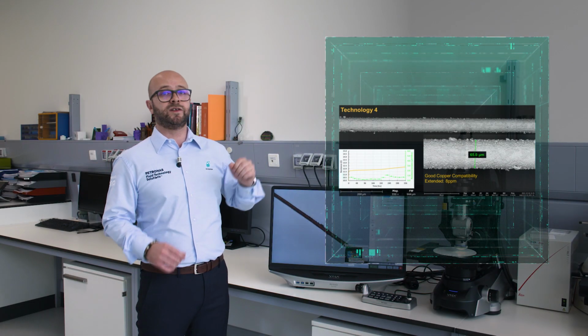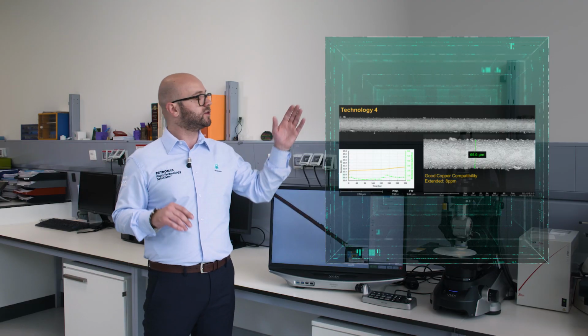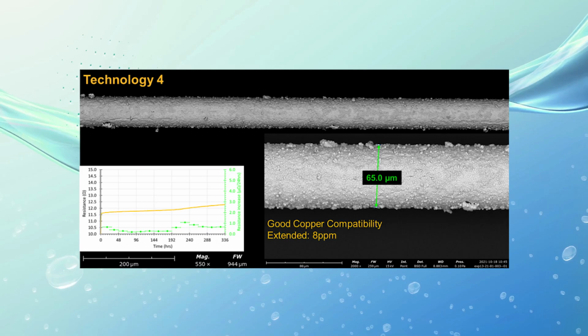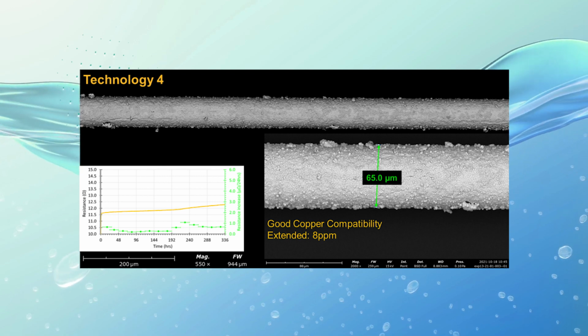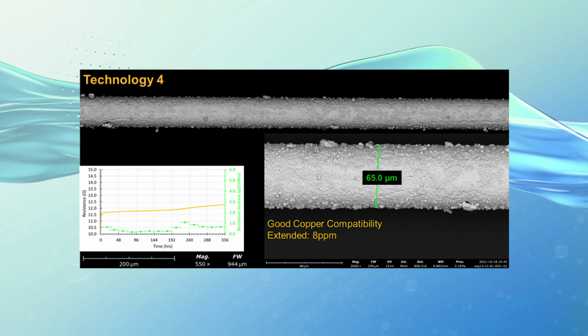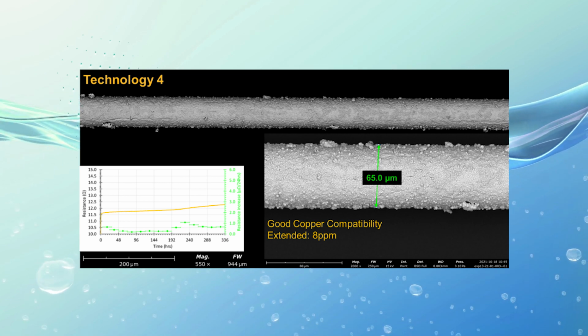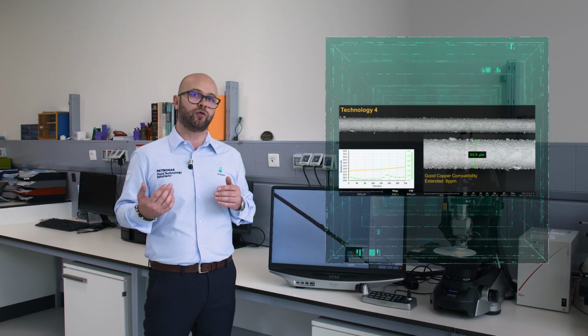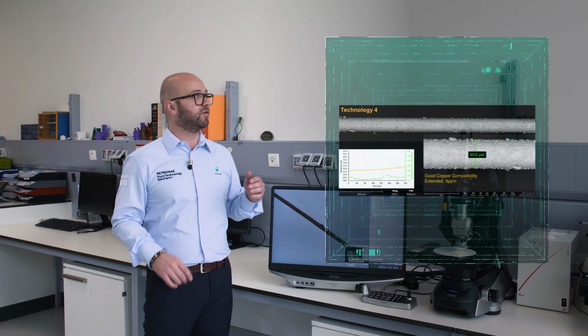For technology 4, the situation is different. The corrosion products that are deposited on the surface are much less thick. We are talking about a 65 micrometer thickness layer, which is homogeneously distributed on the wire. For this reason, in this situation, we don't have any mechanically induced stress that might lead to the rupture of the wire.